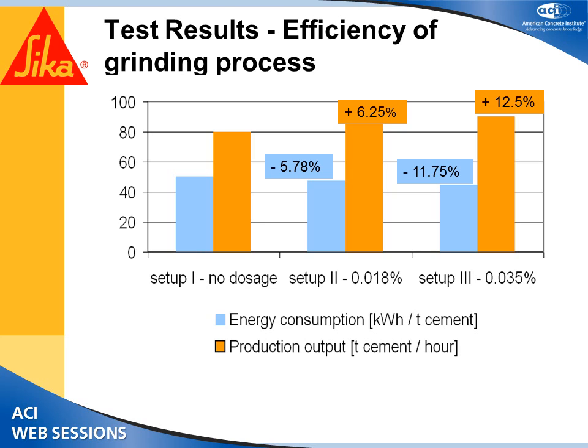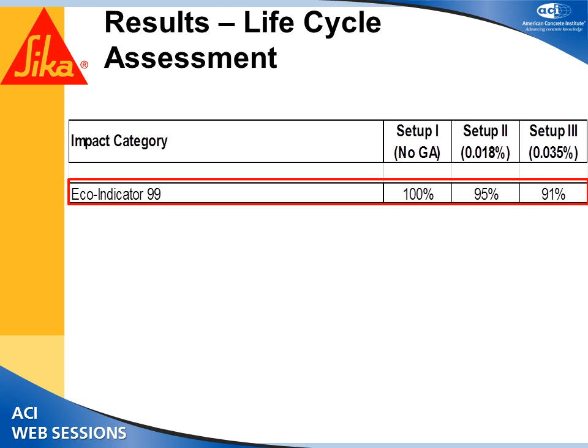Here you have in the blue bar the energy consumption and in the yellow bar the production output. This was when no grinding aid was used. This was when the grinding aid was used. You can see the energy consumption reduced by 5.7% and production increased by 6.25%. And when the dosage of grinding aid was increased from 0.018 to 0.035, you had still increased production and lower energy consumption. So when the LCA was run, in this case it was run only with the Eco-indicator 99.